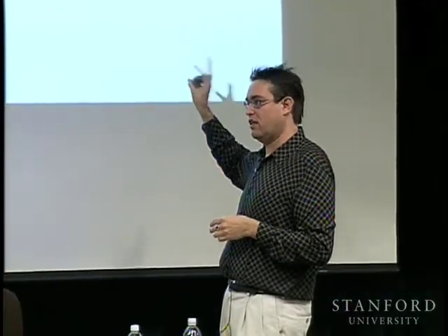So in a typical experiment, where you have a structure that otherwise does not have problems, which I'll define what I mean by in a second, the long strand comes from the biotech company we buy it from, and 95% of them are intact and pristine, and so 95% of the structures that you get are what you want. And if you did a better job purifying that starting material, you would probably do much, much better.